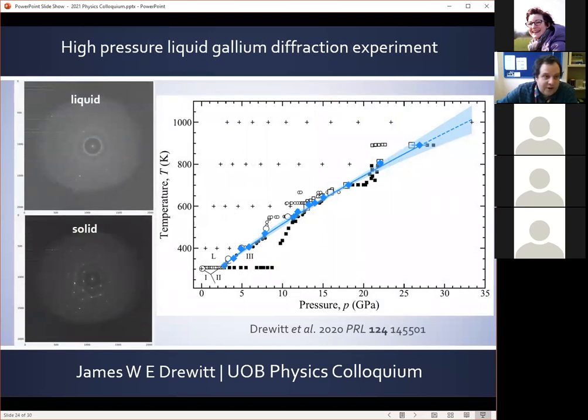So here I show the experimental and simulation conditions explored. So our experimentally obtained melting curve, shown here in blue, was constrained by observing either liquid diffuse scattering or single crystal diffraction, shown here. So each data point here represents either a liquid or a solid measurement, where every 2 to 3 gigapascals we measured long 20-minute acquisitions in the liquid field. And the crosses here represent the pressure temperature conditions of the simulations.